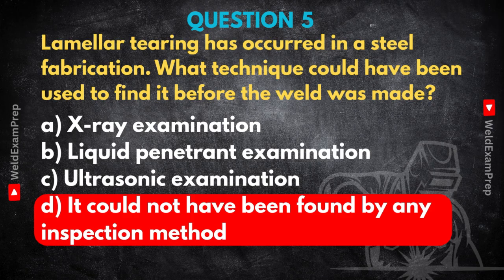Since the tear is a result of the welding stresses acting on susceptible material, it simply doesn't exist before you make the weld. So pre-weld NDT methods like X-ray, LP, UT, they look for existing flaws. Correct. They can't find a tear that hasn't happened yet. Okay, so what does this mean for you as an inspector? You can't find the tear beforehand, but you know it's a risk with certain materials or joints. If pre-weld inspection for the tear is out, what are the key preventative things you should be looking for in the WPS or material certs?